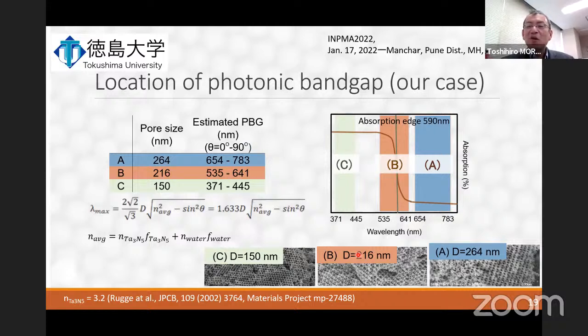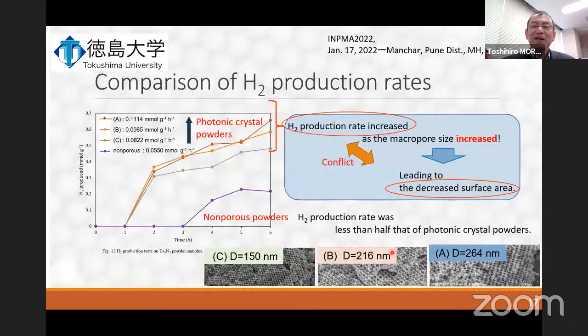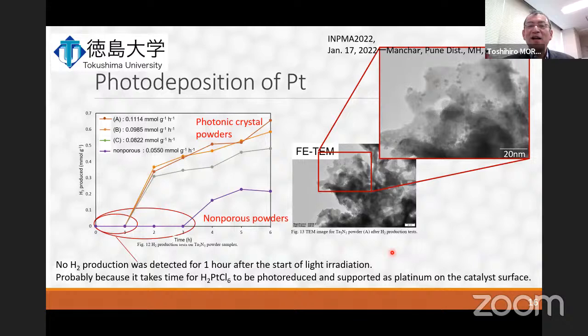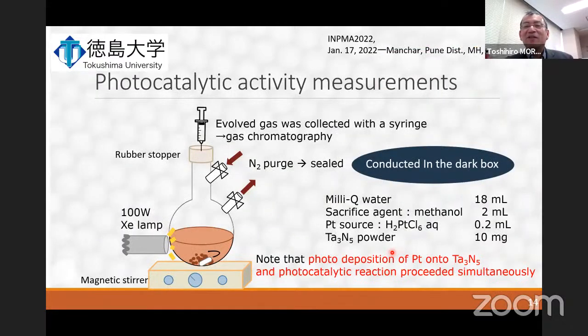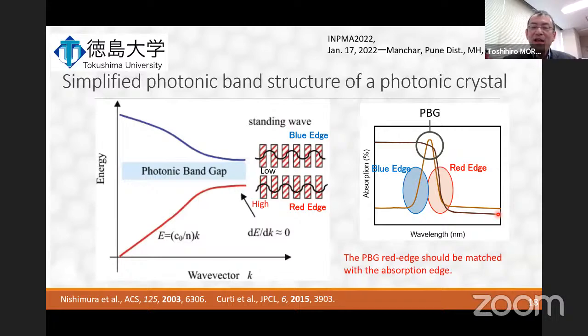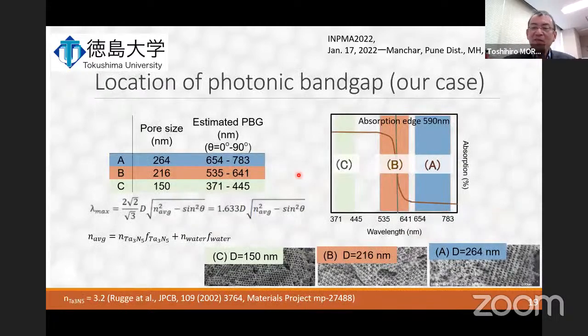Ideal. The void of the inverse opal structure was filled with 10% methanol-containing water, as shown before. You remember this one? 10% methanol in water, okay? And we also assume that the photonic crystal powders were aligned randomly against the incident light, that is, theta ranges from 0 to 90 degrees. Yes, randomly aligned.